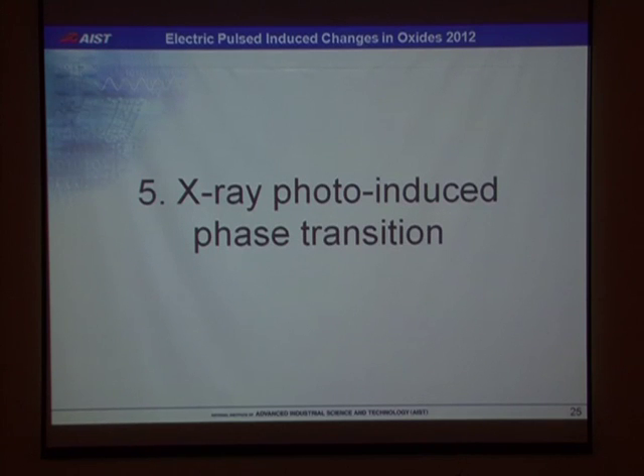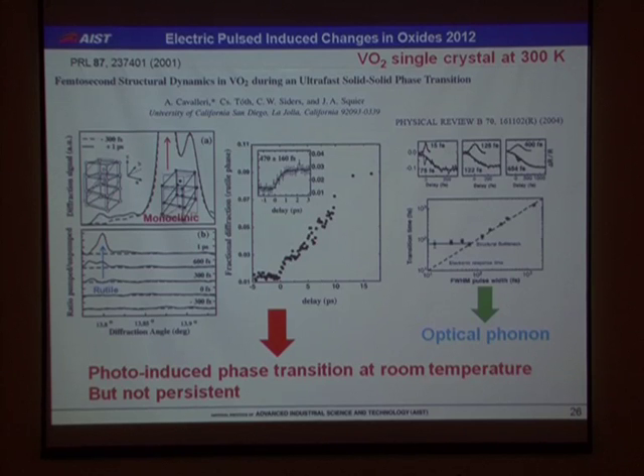So let me move on to the X-ray photo-induced phase transition. This is a kind of photo-induced phase transition. About 10 years ago, Cavalleri reported a photo-induced phase transition using a single crystal at room temperature. They irradiated infrared light, and they measured femtosecond XRD. And this is the low temperature phase, and they clearly see the existence of the rutile phase around 1 picosecond. And unfortunately, this state is relaxed within several nanoseconds. So this is not a persistent phase transition.